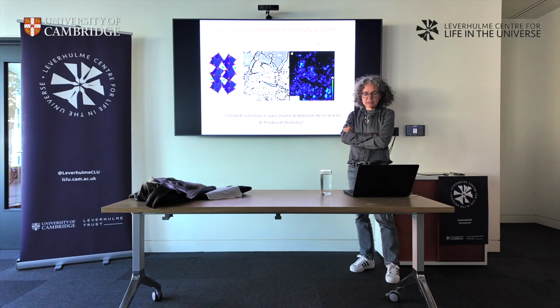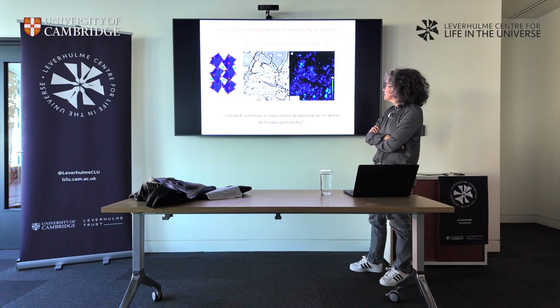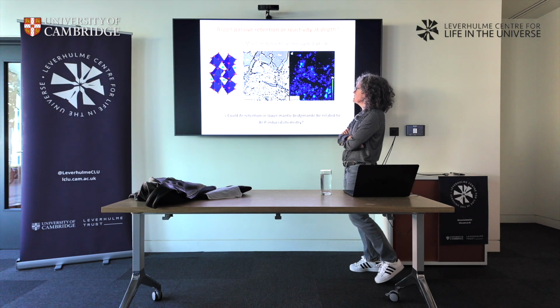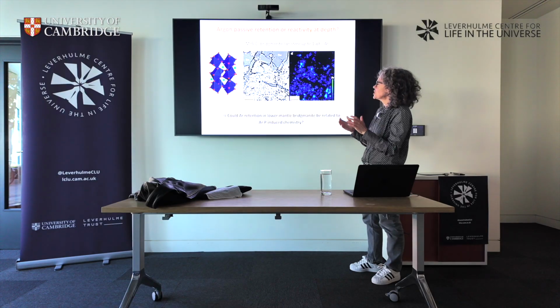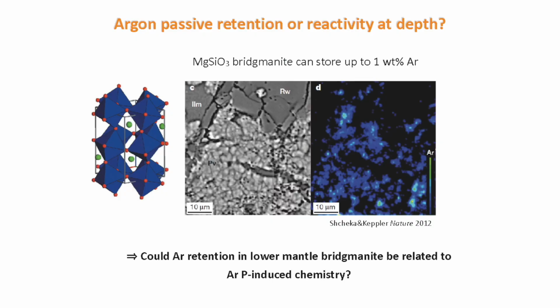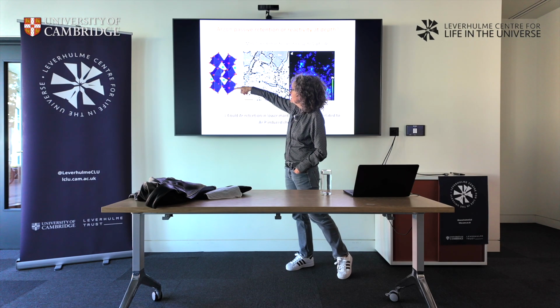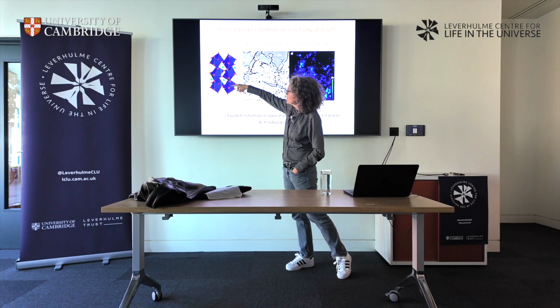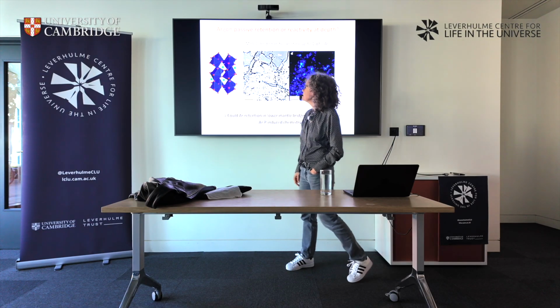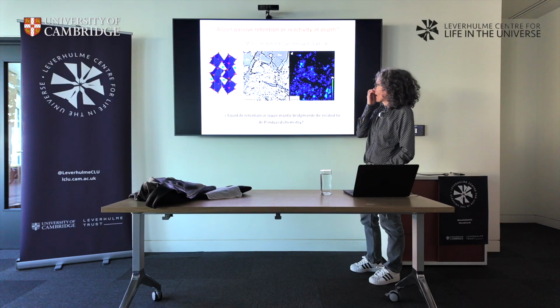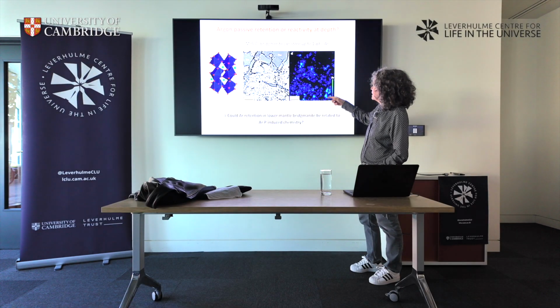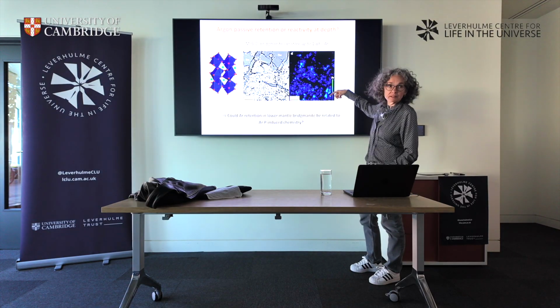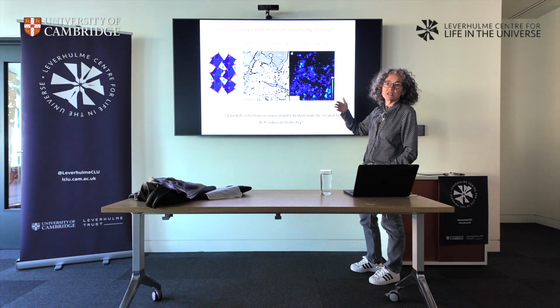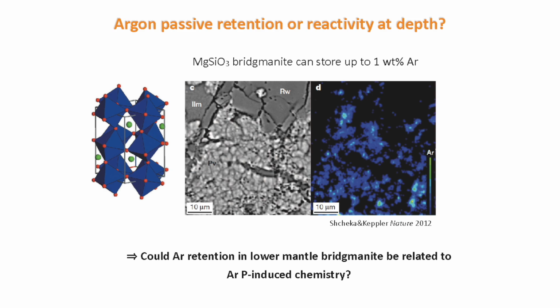Then there was this paper from the Bayerisches Geoinstitut in 2012. Those are large volume press experiments, and they squeezed silicates. They reached the bridgmanite field. Bridgmanite is the lower mantle phase, and the basic unit here is not SiO4 anymore, but SiO6, so silicon sits in an octahedral site bonded to 6 oxygens. In this phase, they measured up to 1% argon, so a lot of argon in this phase. Maybe the guy was right. Maybe you can make some ArO6.